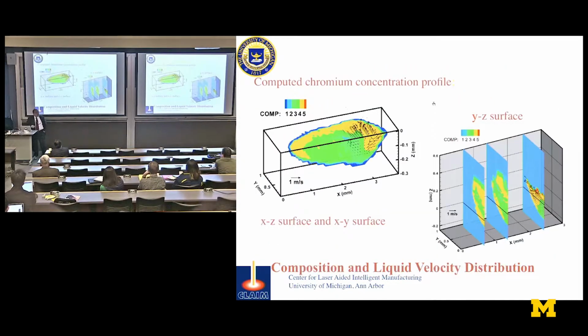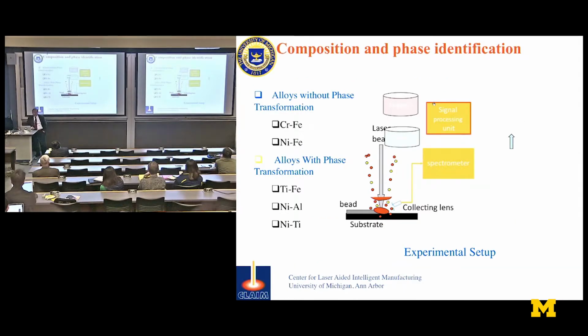And using this model, I can measure the composition, whichever part I'm making. With dissection, we can get the three-dimensional information of the composition distribution and the phase transformation. Now, how do I get the phase transformation? First, start with the composition. We have chromium iron, nickel iron. This is basically without phase transformation. And we take three other systems which have phase transformation.